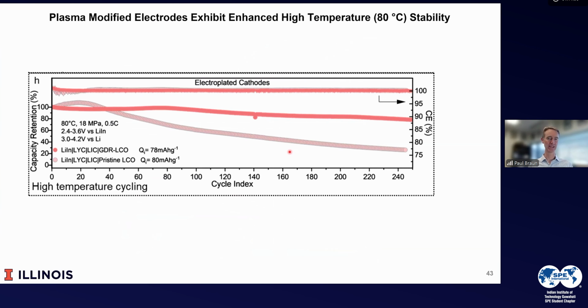And in fact, even at high temperatures, it's quite stable. So this is sort of an aggressive treatment. And what we see is that with pristine material, again, it fades, whereas using the material that has been surface treated, there's almost no fade.